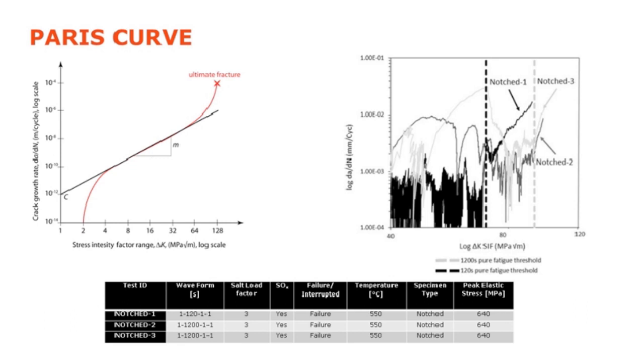However, there becomes a point, at a certain crack depth, at which the crack then starts to grow more in line with fatigue. So when we look to the right of that threshold line for the notch 1 specimen, we actually start to get that straight line. That Paris curve is starting to come through there. So we can hypothesize that at that point fatigue has become the dominant factor. To the left we've got stress corrosion cracking or time-dependent mechanisms dominating our crack growth, and to the right we've got more fatigue coming into play.